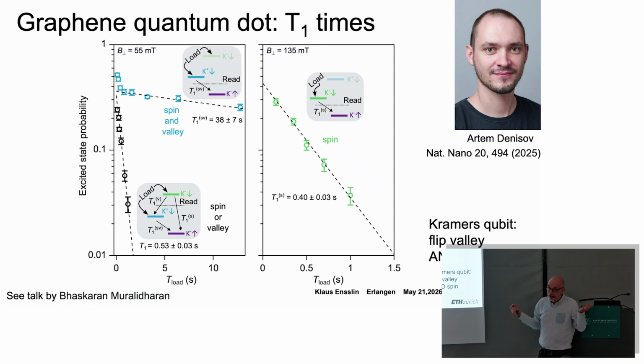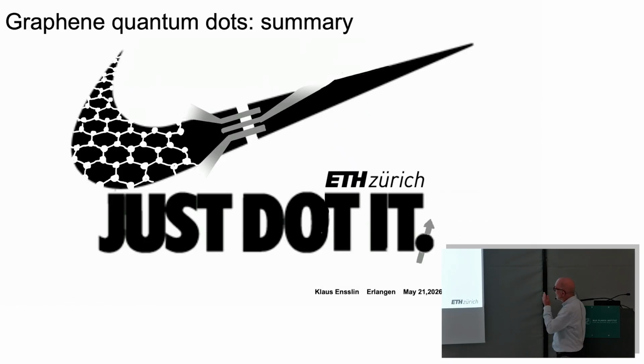Well, graphene is an almost perfect system. It has, at least for these systems, no atomic defect. And that's why it's so hard to get from K to K prime. And that's why these qubits have this very, very long lifetime. And now we call them, to give them a general name, a Kramers qubit, because it's not a valley qubit, it's not a spin qubit. These are just two states that have opposite valley and spin quantum numbers, and that's why their lifetime is so long. So that's, in some sense, a quite unexpected outcome, but it's a very nice outcome, because, and again, it's funny, it goes back to this primitive unit cell in real space that has two atoms. It ends up with a very nice qubit with a very, very long lifetime. Okay, so that's our motto: quantum dots in graphene are just fantastic.